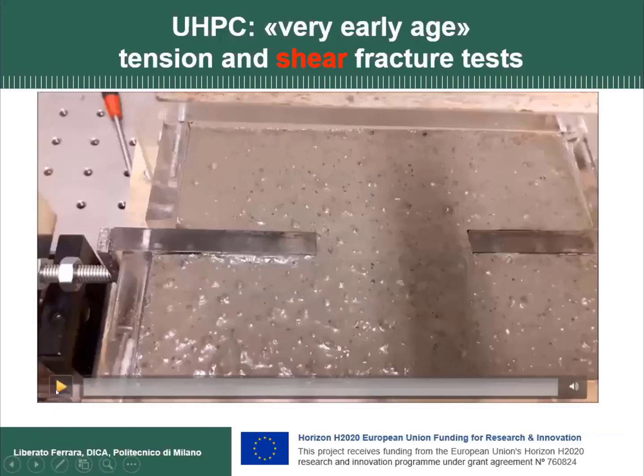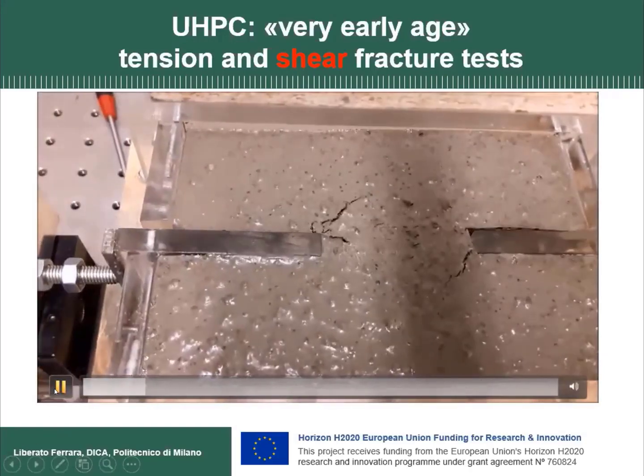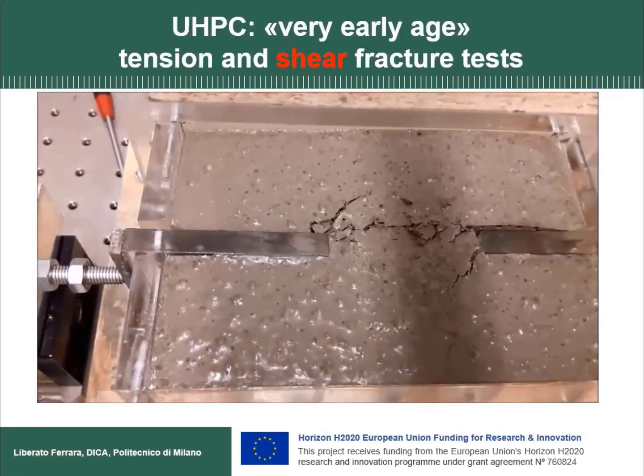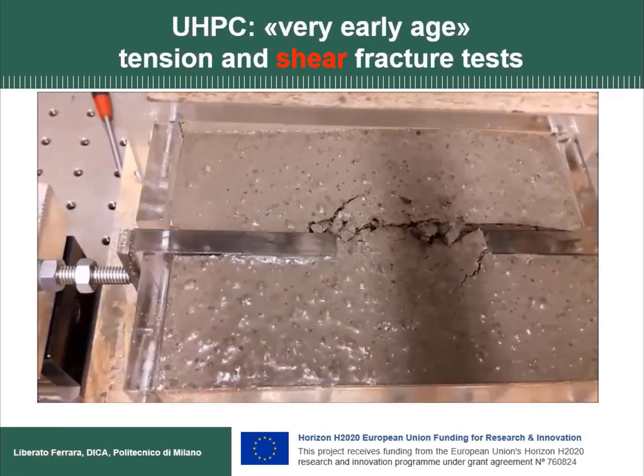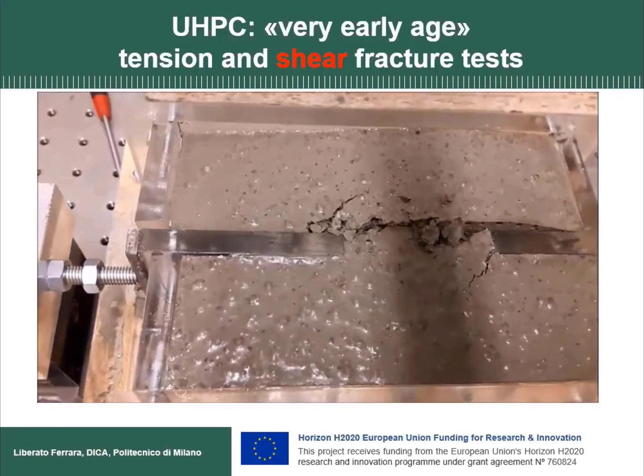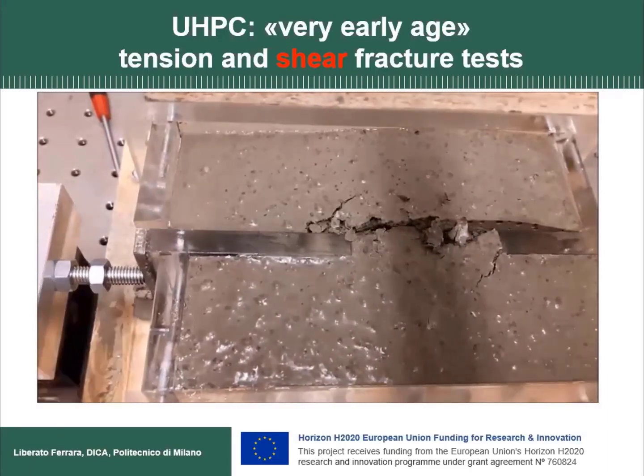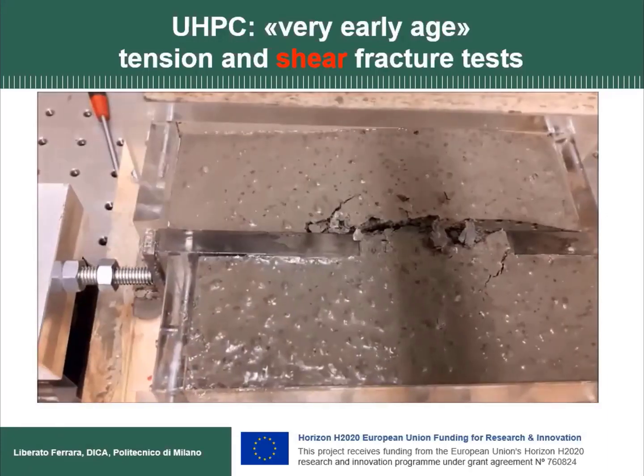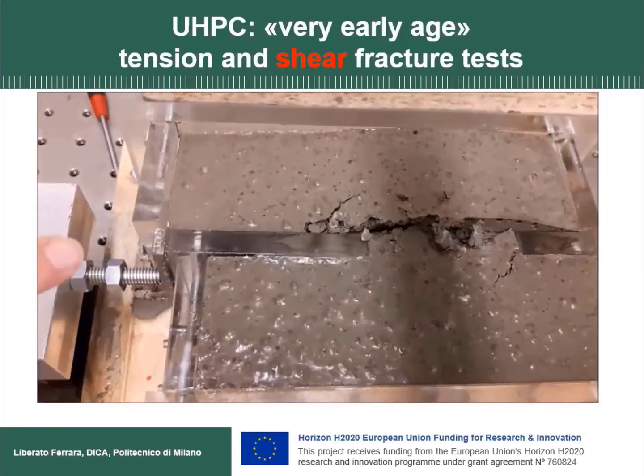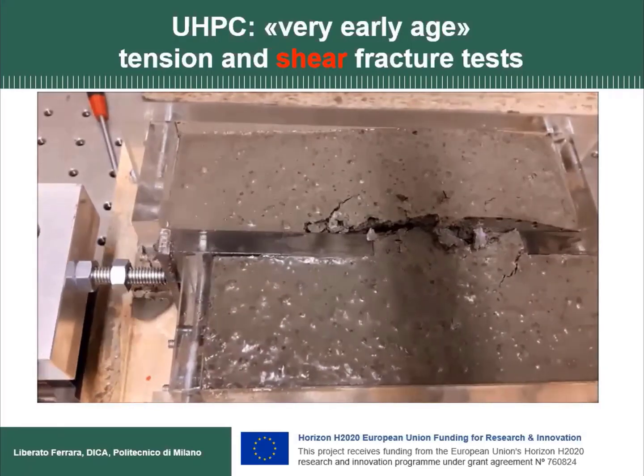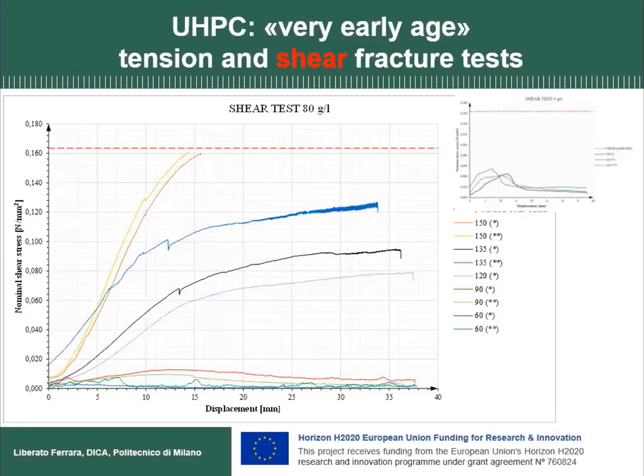So then we went to the shear fracture test. This is another movie. You can see that the shear fracture test starts with a clear onset of the diagonal cracks from the notch tips, and then you have the shearing off of the ligament cross section with complete separation of the two specimen halves.